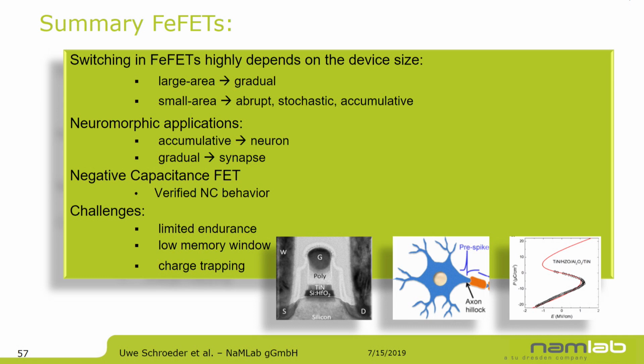if you're trying to switch one memory in the whole array, you have to apply certain voltages. And the problem currently we have is a disturb issue: if you want to switch one device, you have a little bit of sub-threshold switching for another device, and this is limiting the behavior in a complete array. So I think the FeFET array is a little bit critical. I would probably vote for the 1T, 1C cell, because in this case you have an access transistor which avoids any gradual switching of your capacitor structures.